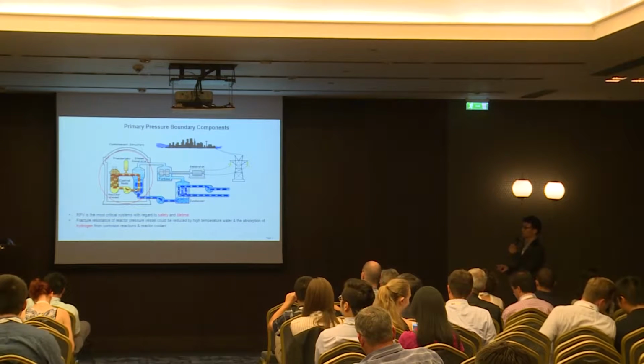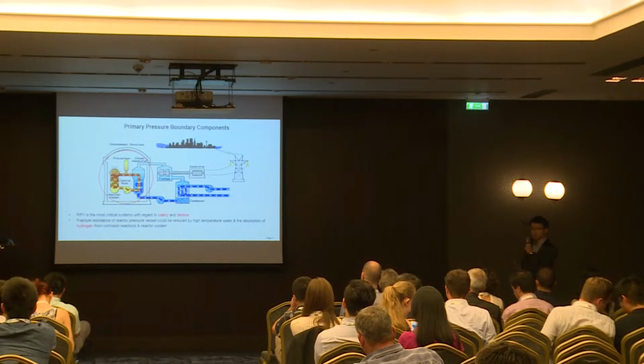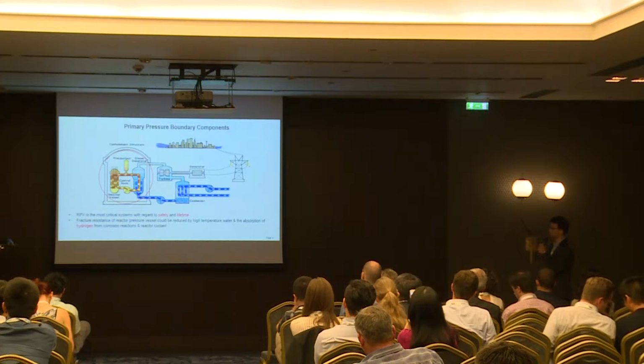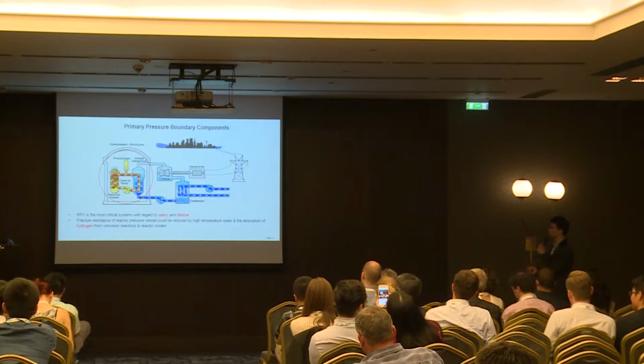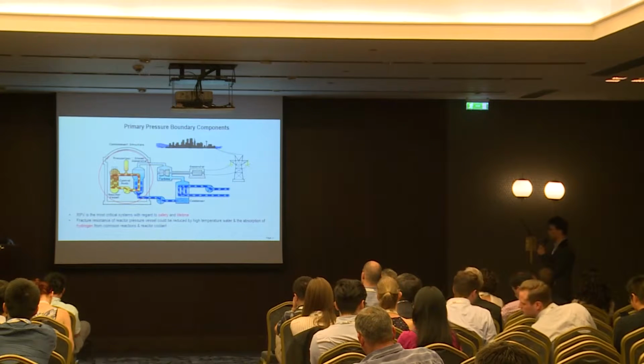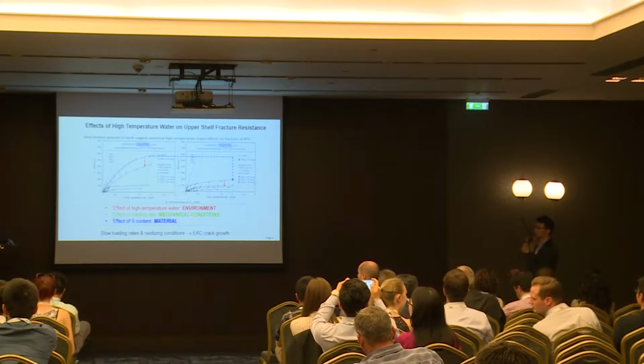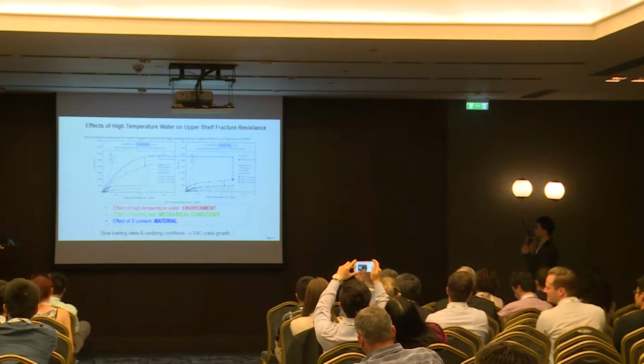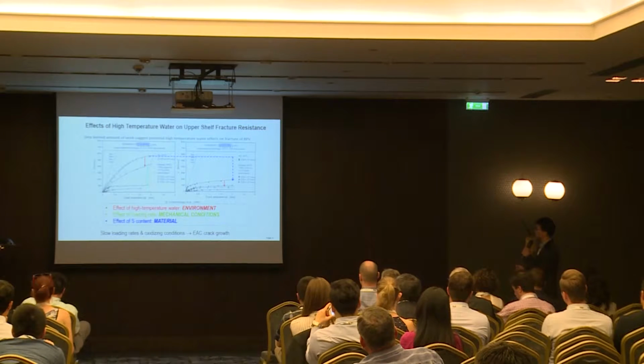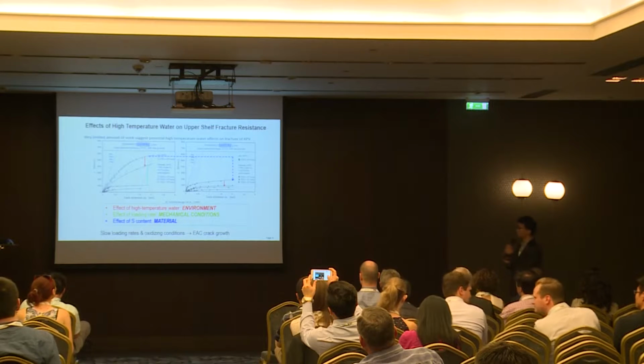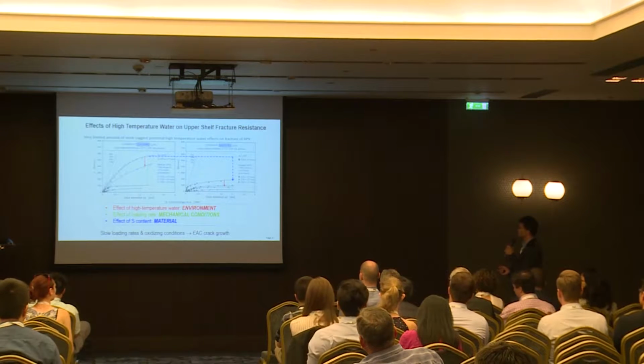Basically, most of the investigation on the degradation of the fracture behavior of RPV was related to irradiation. Not too many results were published on the high temperature water and hydrogen effects. And this is a study back in 1994. The figure on the left describes the J curve for the low sulfur steel, and the figure on the right was for high sulfur steel.